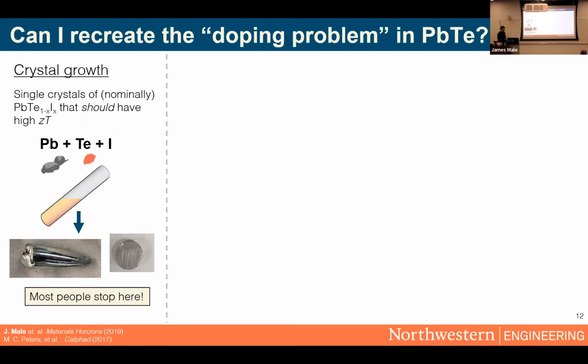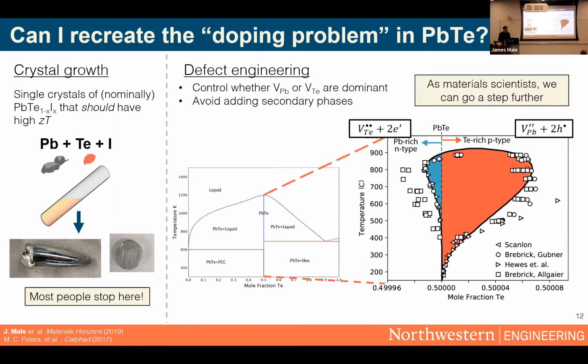What I wanted to do in this project is take one step further and use some basic aspects of material science to do a little bit more defect engineering in these samples. So using our familiar material science tools like phase diagrams, we can look at a phase diagram of lead telluride at a normal scale and see that the 50-50 lead tellurium composition looks like an infinitesimally narrow line, or a line compound. However, as I mentioned, entropy is requiring us to have defects in the lattice.